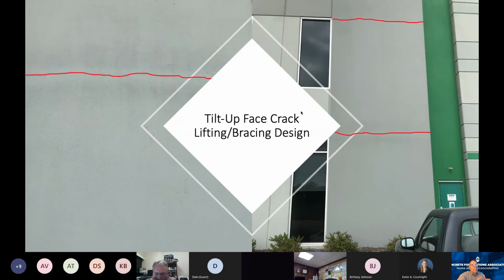Now, I have seen what you're questioning. I have seen structural panels with horizontal cracks on the inside, and those largely come from that same condition. But that's when you're dealing with a solid thickness panel, not an insulated panel, and it's generally when the modulus of rupture is assumed higher or counted on, or not delivered to the design specification, and you end up getting greater vertical flex, and it begins to fold. And so then in a structural panel, if that happens, or a single thickness wythe, you are going to get that crack that will propagate through to the inside face. Really good question.